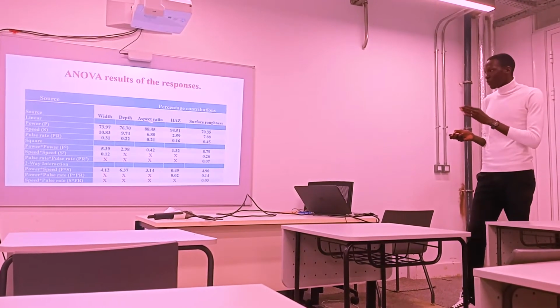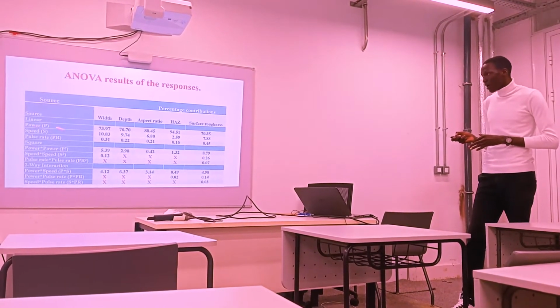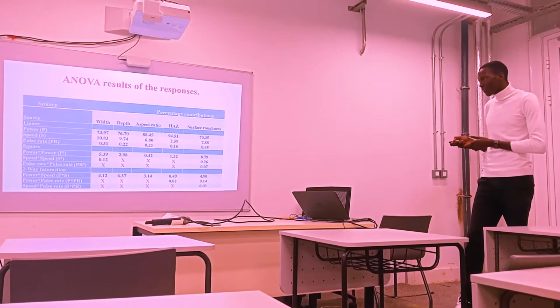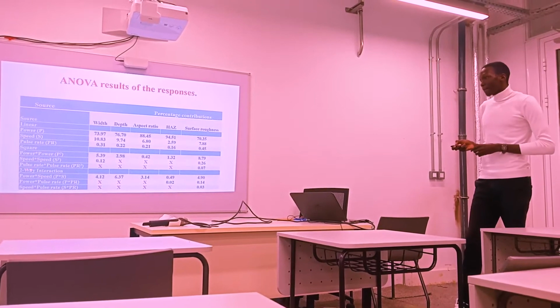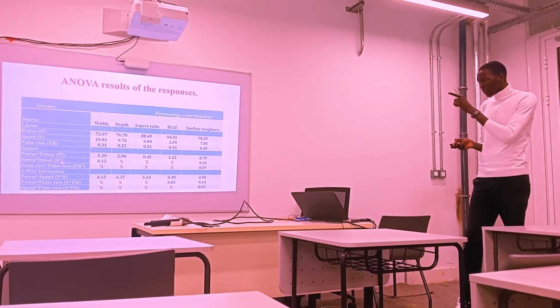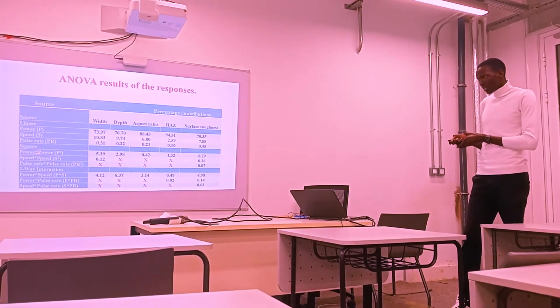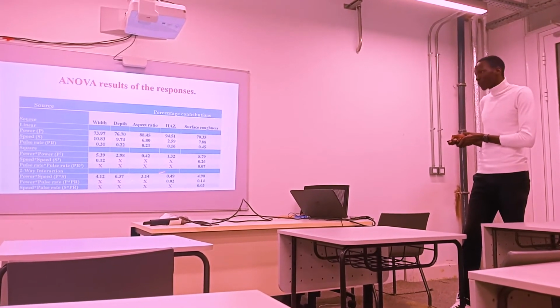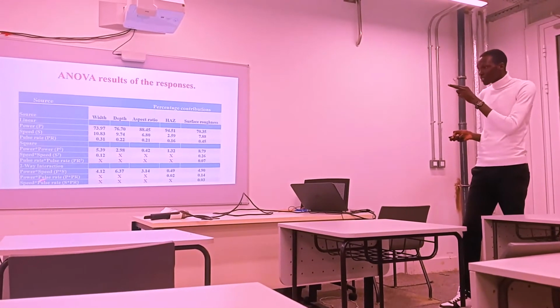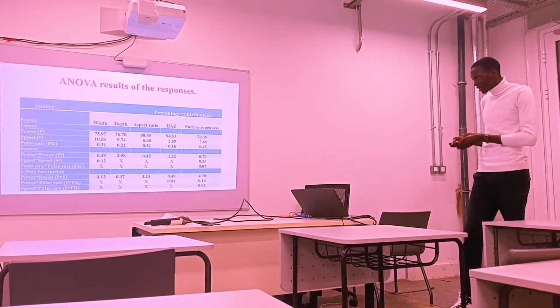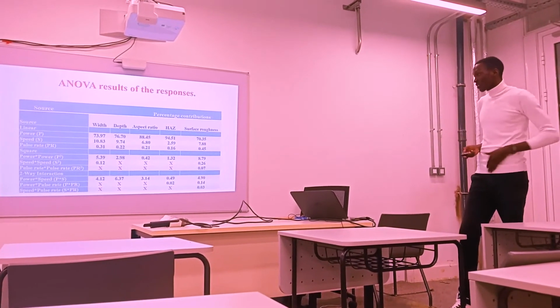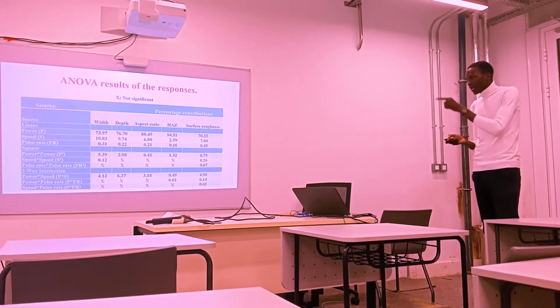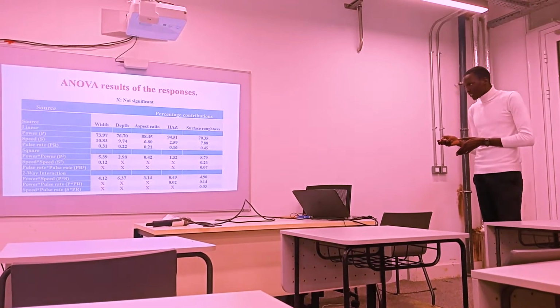So, for example, for heat affected zone, power was significant, speed significant, pulse rate significant, but the square of the speed was not significant, and the square of the pulse rate was not significant. And also, the interaction between the speed and the pulse rate was not significant. Now, X represents not significant in this table.